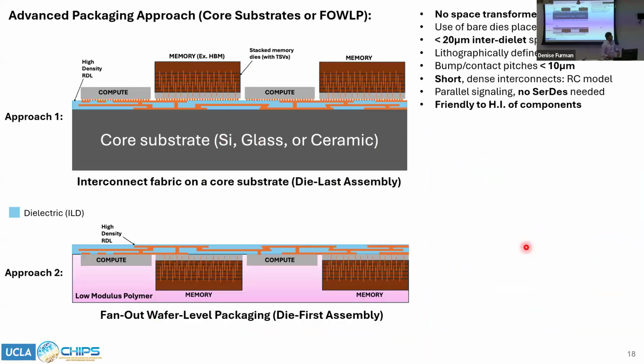So now let's talk about how advanced packaging can be used to overcome what we do with conventional ways of doing it. In advanced packaging, there are two ways of doing this. The first way, which I'll call die last assembly, is also called interconnect fabric on core substrate. The second approach is fan-out wafer level packaging, which I'll call die first assembly. In the first approach, you start with the core substrate, which could be made of silicon, glass, or ceramic. Then you use microprocessing, so back end of line processing, to build high density interconnects on top of this core substrate. Then you can take the bare die compute and memory chips and flip chip attach them on top of this substrate.